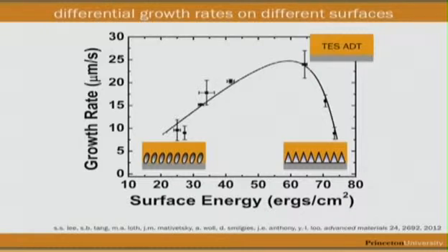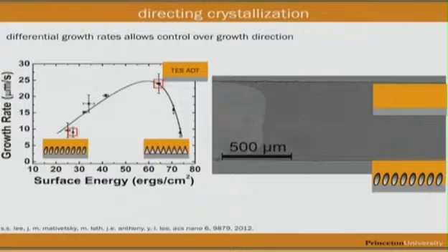So like I showed you before, we can measure the growth rate of TESS-ADT on these different substrates. And so on silicon wafer, the growth rate of TESS-ADT is about 25 to 27 microns per second. It turns out that we can decorate this substrate with different kinds of chemicals before we deposit TESS-ADT, and then we solvent vapor expose it to get it to crystallize. And if we do that, we can reduce the growth rate. So these spherulites, the video that you show, the growth rate is much slower if we decorate the surface. Okay, so this is a hydrophobic surface, and now the growth rate is 10 microns a second. If we make the surface very, very hydrophilic by decorating it with something else, we can also reduce the growth rate.